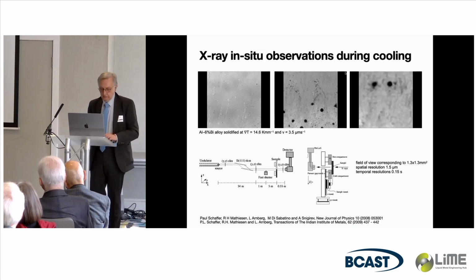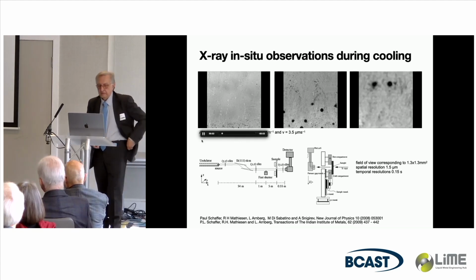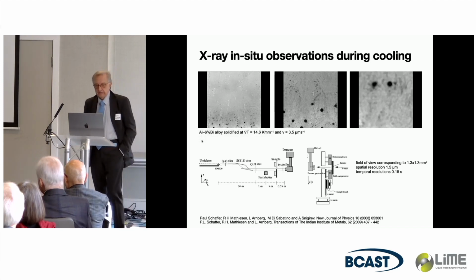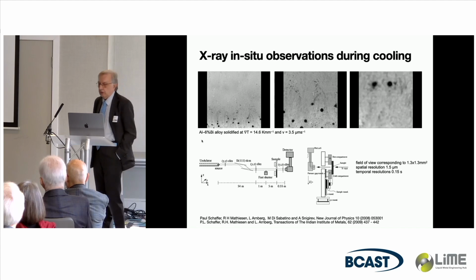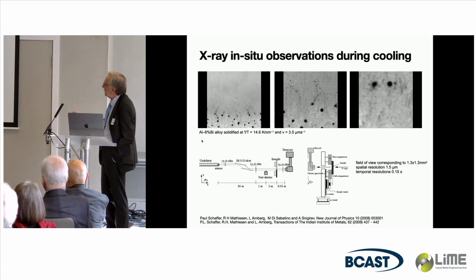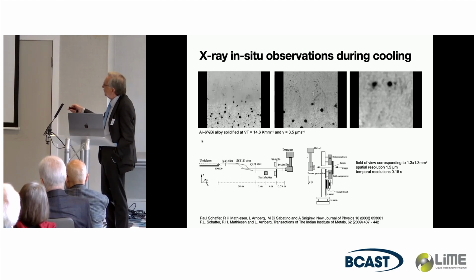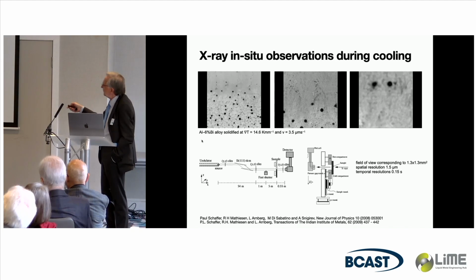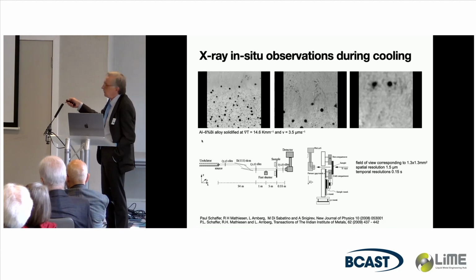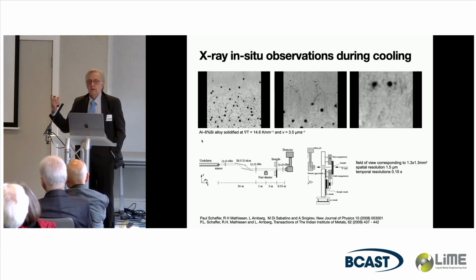So I will show you the movie made by Ragnvald Mathiesen. Yeah, it works. Ragnvald Mathiesen, Lars Arnberg, and Paul Schaffer made it at the beamline in Grenoble. And you see here, cooling an aluminum-bismuth sample, we had a joint project on that. And you see here that the droplets appear in front of the monotectic reaction front. They move a lot, move upwards, which is Marangoni motion. And you later see, if they collide, I show it later here, if they collide, yep, they go down, and everything which goes up dissolves, because it's hotter there, the solubility is better.